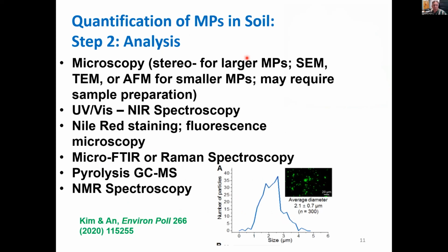In terms of analysis, this is really the toolbox that's used in the micro size range. Microscopies are a workhorse. Larger particles, stereomicroscopy is very sufficient. When we start getting into tens and single microns, then we need things like SEM and TEM and AFM that the previous two panelists have talked about. We also, our group, are working with UV-Vis-NIR, looking at the whole spectrum, which has a fingerprint. We can identify the plastic type, as well as get information about size and concentration.